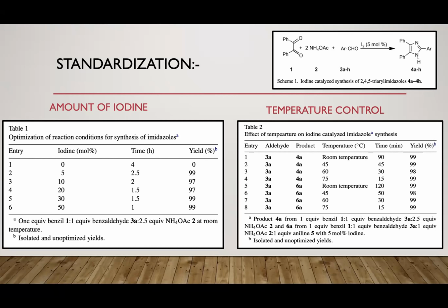After standardization of iodine, various temperatures were tried. In order to examine the effect of temperature, the concentration of iodine was kept constant at 5 mole percent, and the reaction was monitored at different temperatures. You can see it in the other table on the right-hand side. At elevated temperature, using 5 mole percent, better results in terms of yield and reaction time were obtained.